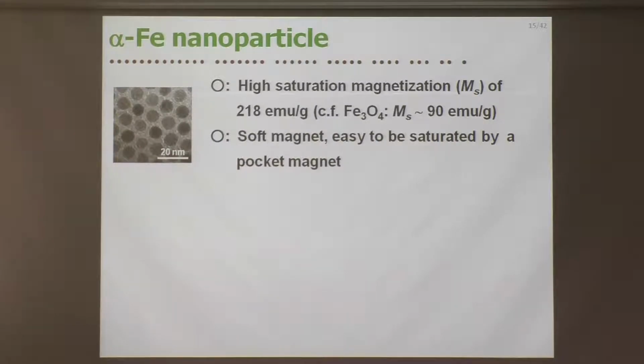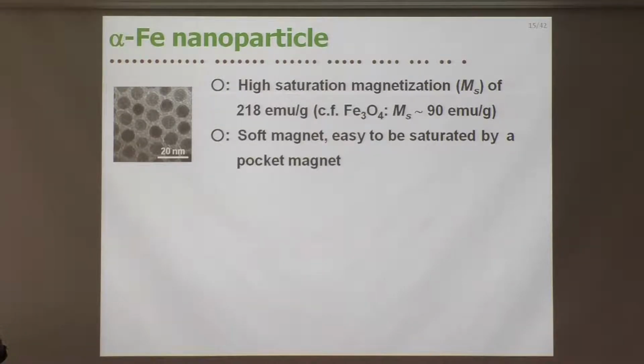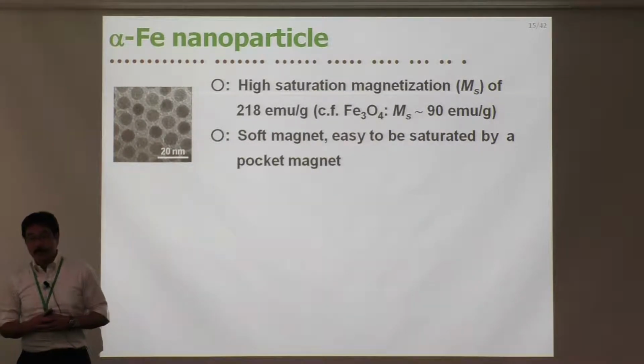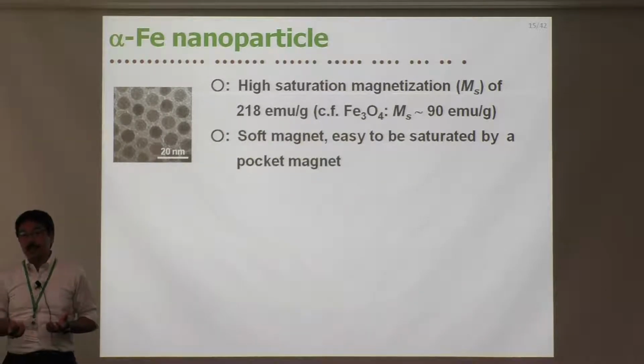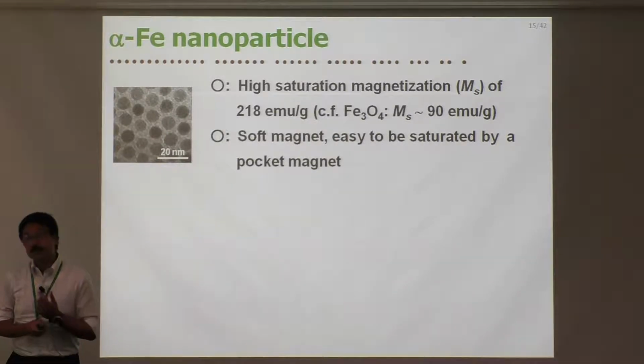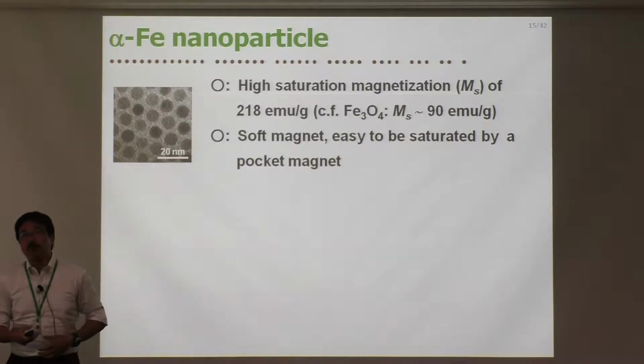Let me first explain why I chose alpha iron nanoparticles. Because, as you know, alpha iron is known to have very high saturation magnetization of about 200 to 220 EMU per gram, which is more than twice that of the conventional magnetic material, iron oxide magnetite. And alpha iron is known to have rather soft magnetic properties and is easy to saturate even with a small magnet. Yes, alpha iron has many good points.